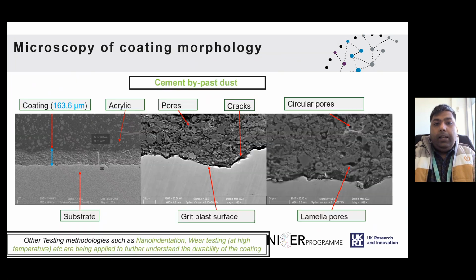And finally, we also started to perform the scanning electron microscopy studies to understand the morphology and the thickness of the coating. So one can see the coating thickness, which is shown here to be about 163 micron, the type of pores and the cracks, etc., that one can expect to see in a thermal spray coating, which is an atmospheric deposition process. It does not include vacuum or anything. So obviously the splat that forms along each strike can have some sort of non-uniformity, and those can well be studied through tools like the scanning electron microscope, which are shown here.